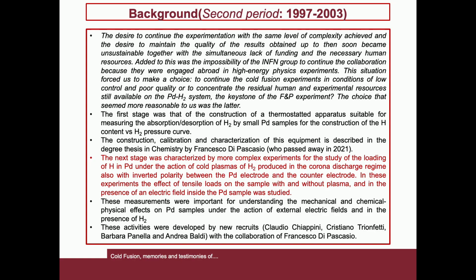These measurements were important for understanding the mechanical and the chemical physical effects on palladium samples under the action of outer and inner electric fields in hydrogen. These activities were developed by new recruits who over time took turns to obtain the degree in chemistry: Claudio Chiappini, Cristiano Trionfetti, Barbara Panella, and Andrea Baldi, with the collaboration of Francesco Di Pascasio.